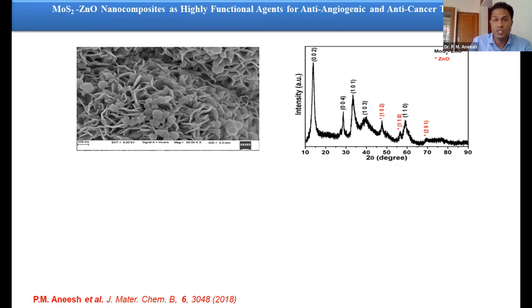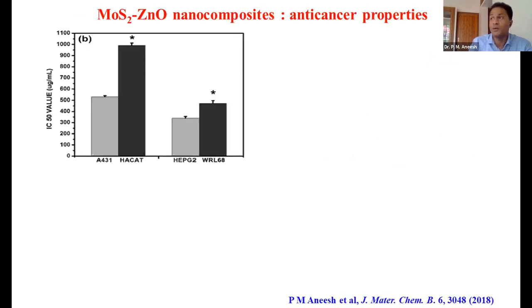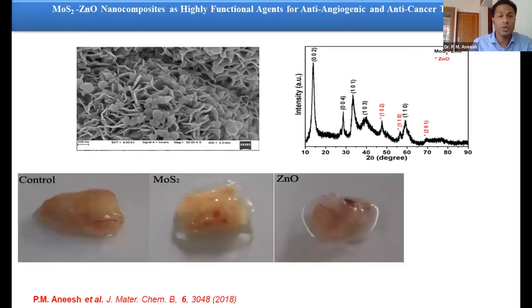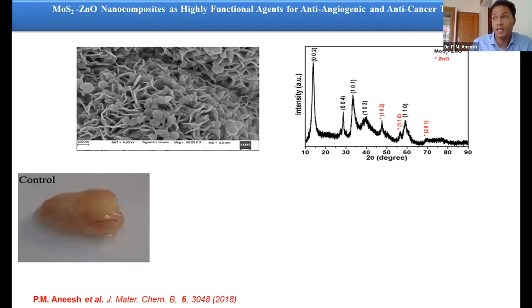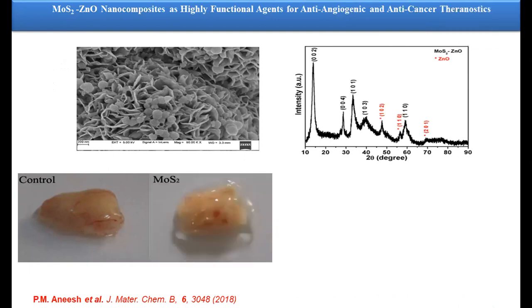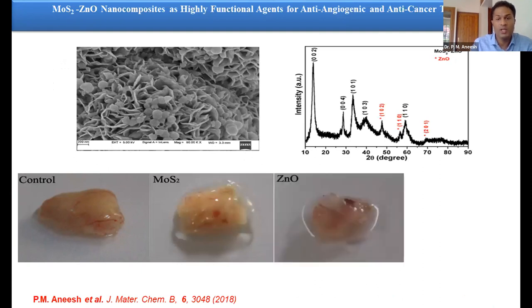We checked the cytotoxicity measurements of this sample with the normal cell line and the corresponding cancerous cell lines when treated with the MoS2 nanocomposite, and we found a safety index of 2. Later we checked the sample for anti-cancer property, on cancerous cells, using the xenograft assay. This is the control, and you can see that when it is treated with the MoS2 sample, the size is reduced, and you can see the hemoglobin content as well. When you treat with the zinc oxide sample, the size is reduced here also, and you can see a little bit of hemoglobin content.